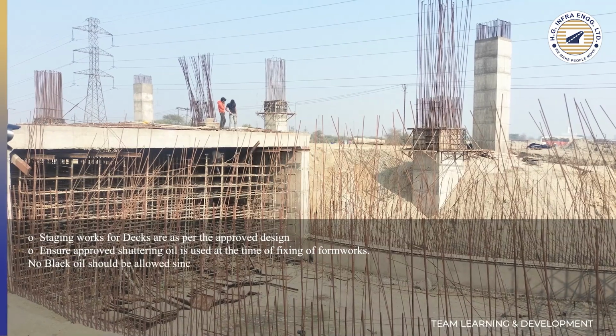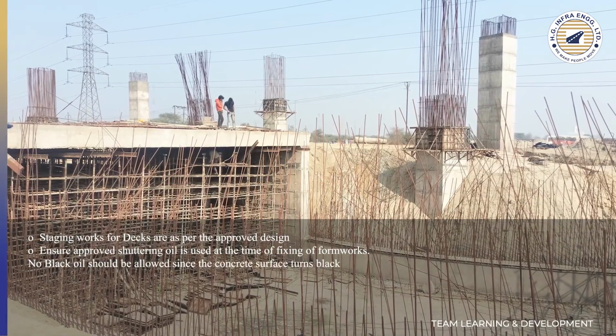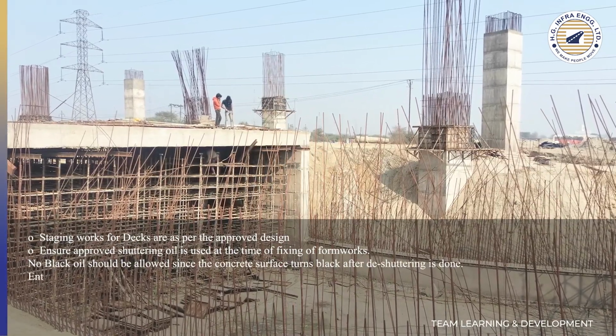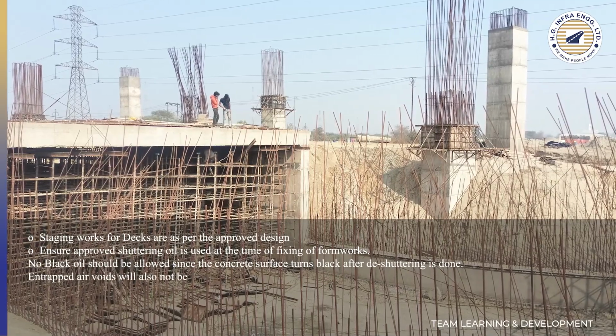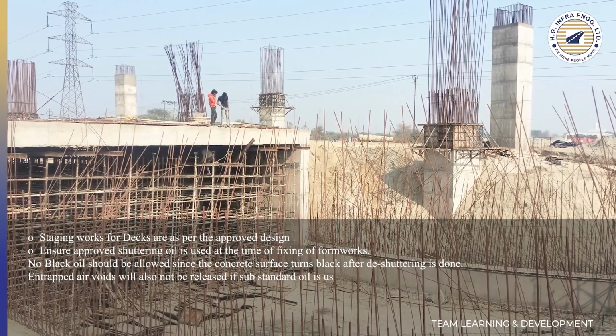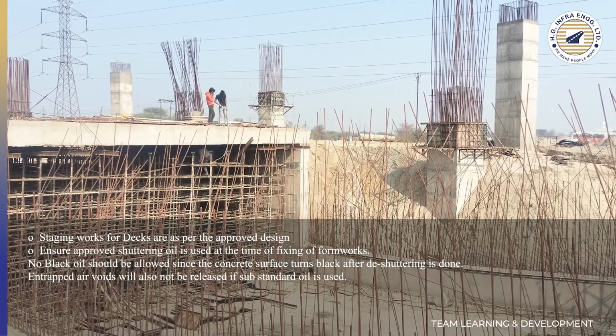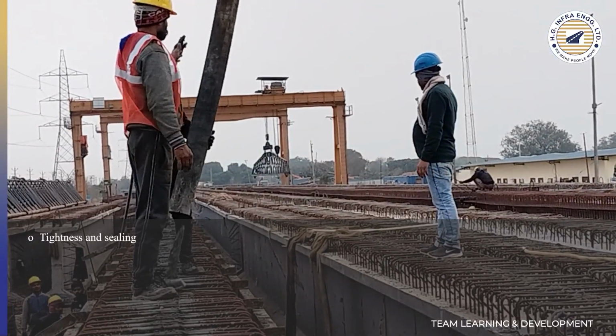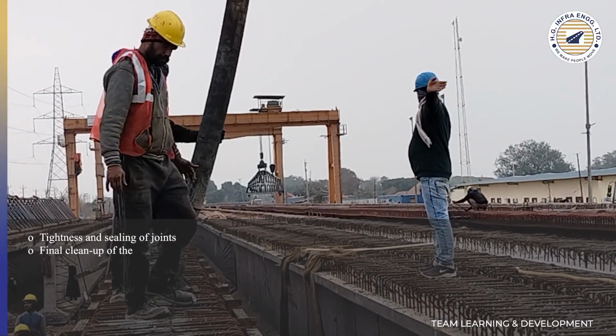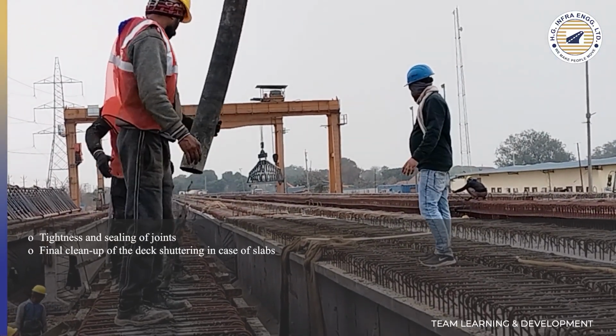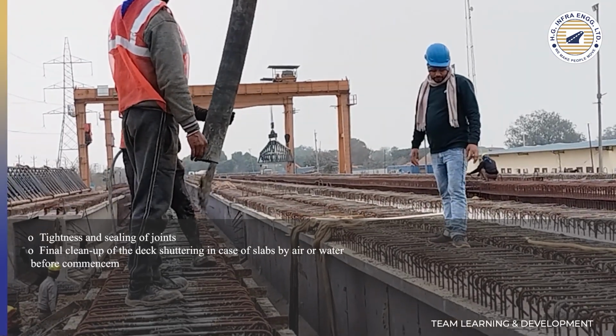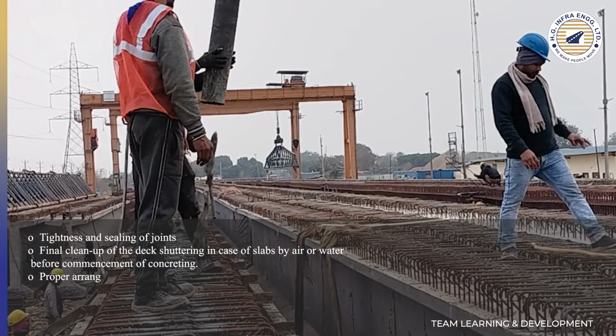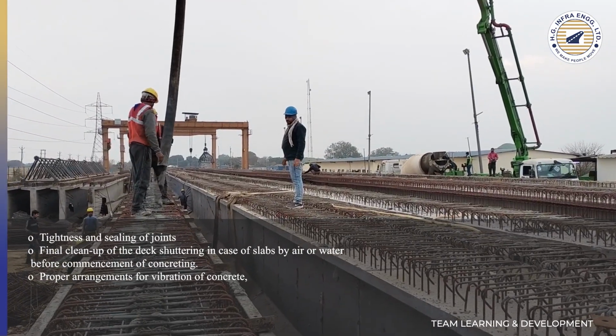No black oil should be allowed since the concrete surface turns black after de-shuttering is done. Entrapped air voids will also not be released if substandard oil is used. Tightness and sealing of joints. Final cleanup of the deck shuttering in case of slabs by air compressor or water jet before commencement of concreting.